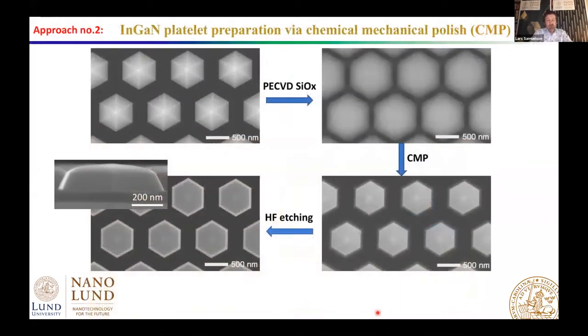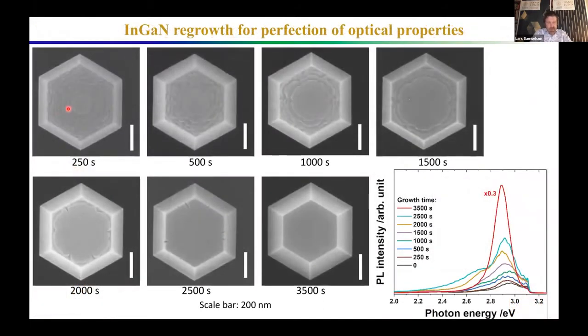So the second approach is the one where we use chemical mechanical polishing. You have the pyramids again, you embed them in silicon oxide, you do this CMP, and then you have the platelets here, and then you do HF etching to remove the silicon oxide, and here are the platelets. Platelets are not fully flat because of the mechanical polishing, which leaves some curvature on the top surface.